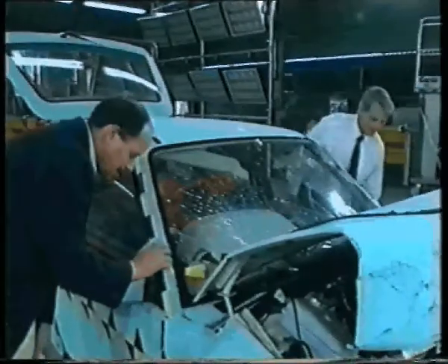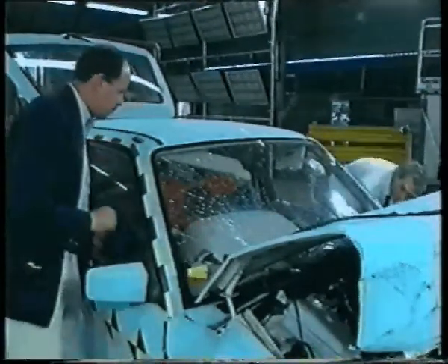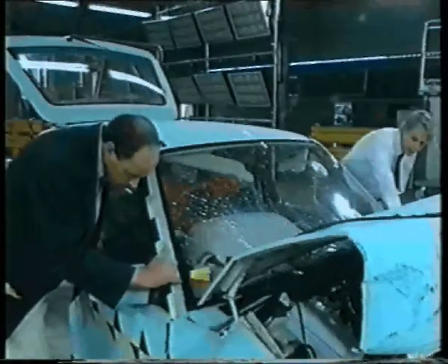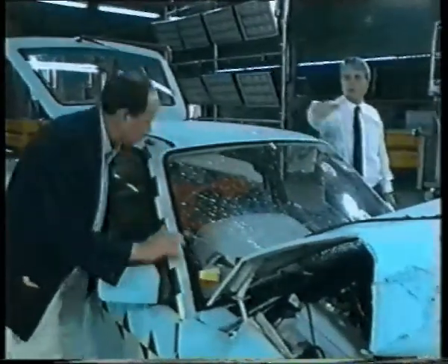The main criteria being that the screen must be retained by the bonding agent sufficiently to prevent the ejection of any unrestrained passengers and maintain the integrity of the vehicle structure. The screen aperture immediately above the dash was pushed back during the impact, and the film shows that the laminated screen suffered serious damage. However, detailed examination after the impact showed that the Screenfix retained adhesion to the aperture and the glass on both sides and along the top of the screen, which meant that it had exceeded the requirements laid down for this test.